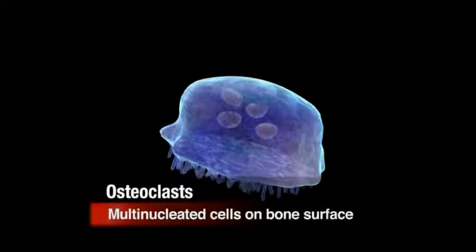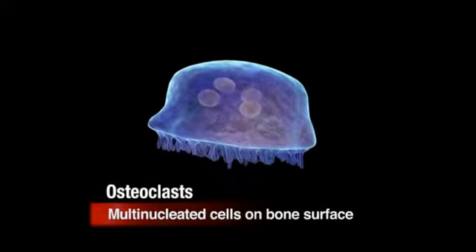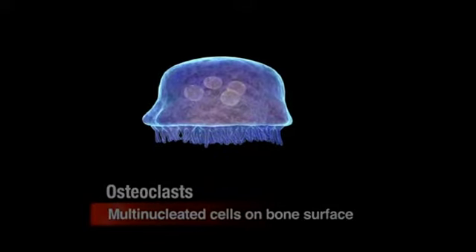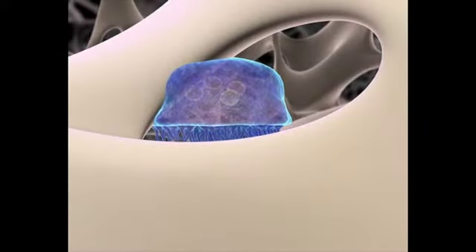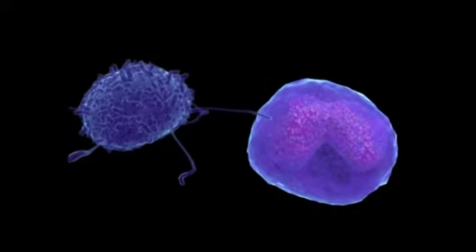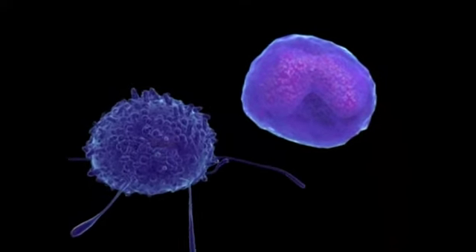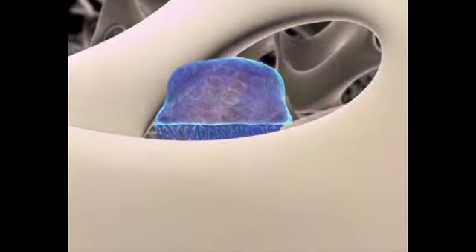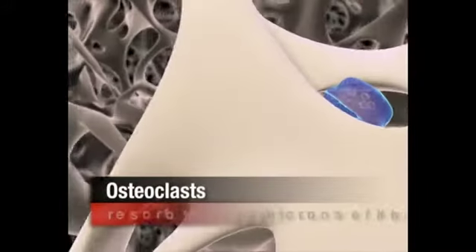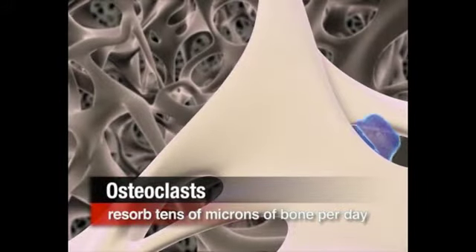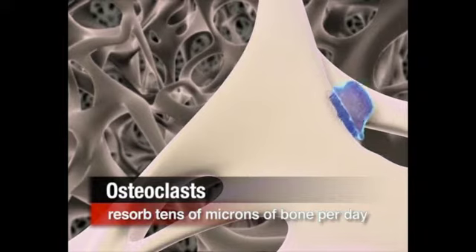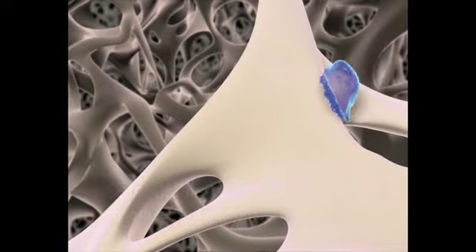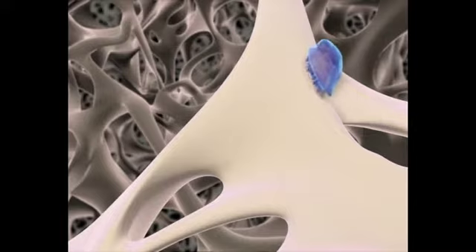Osteoclasts are large, multinucleated cells that lie on the surface of bone. These cells are thought to derive from the fusion of many pluripotential stem cells, such as monocytes or macrophages. They act to resorb bone. Osteoclasts remove matrix by enzyme dissolution and bone by acid demineralization. Osteoclasts can erode tens of microns of bone per day.